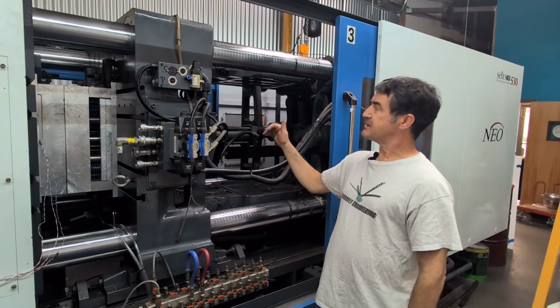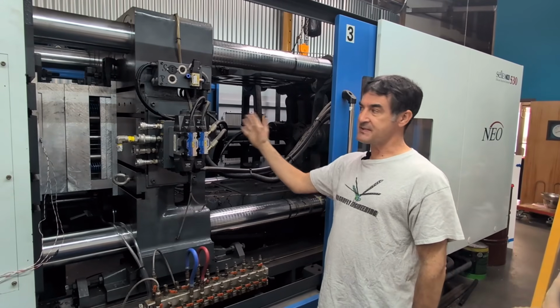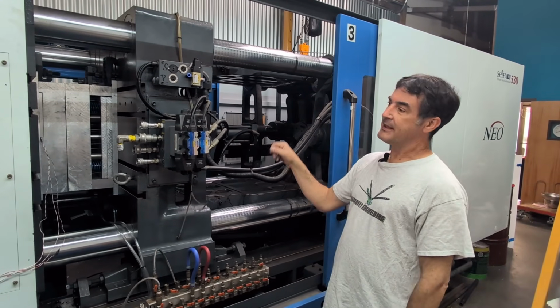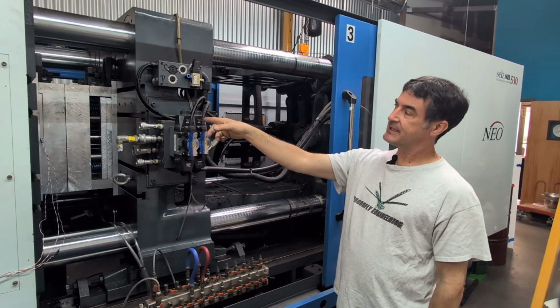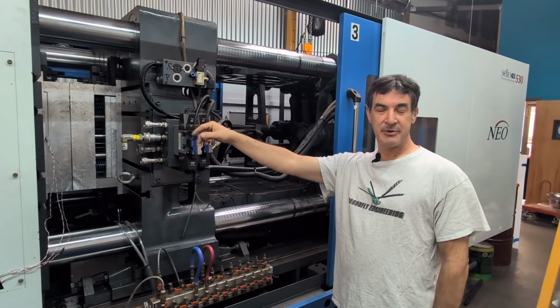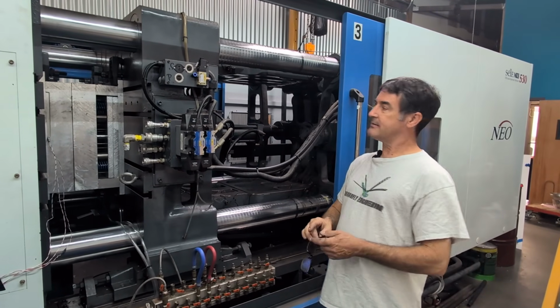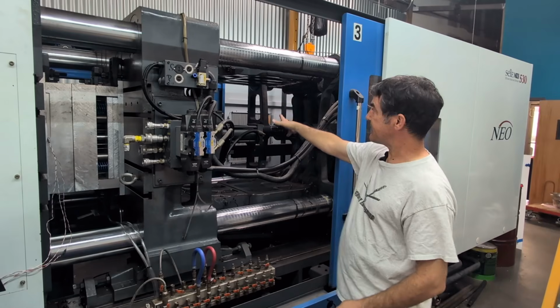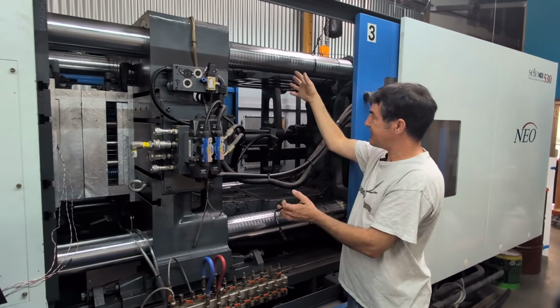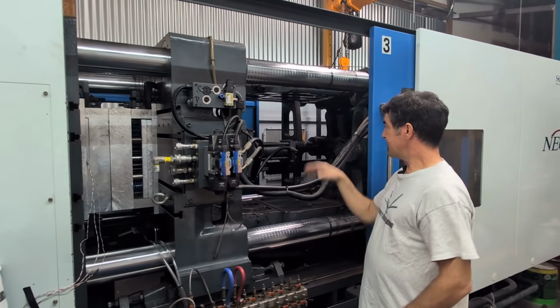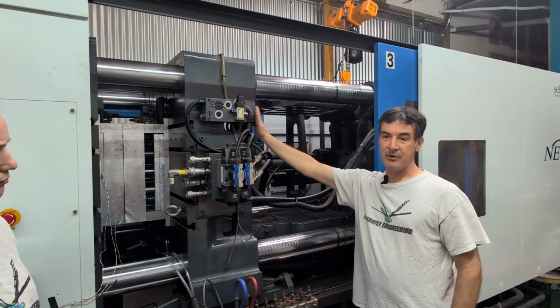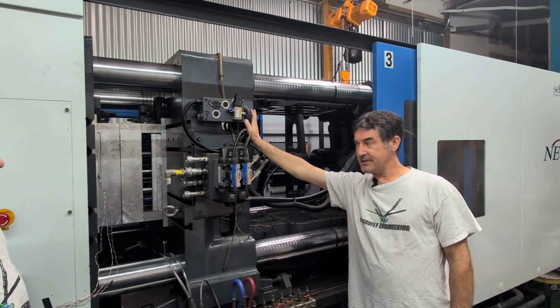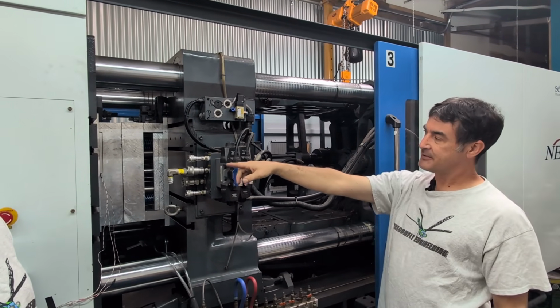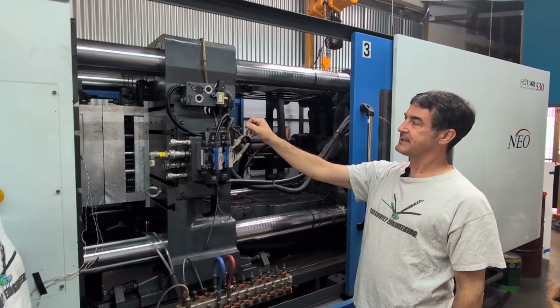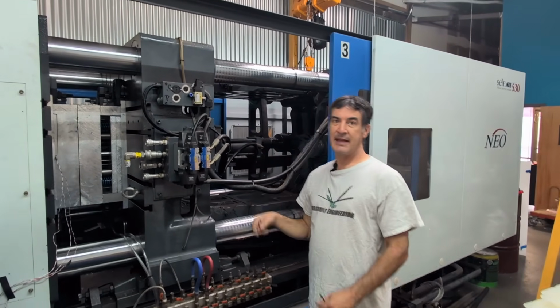So the molding machine clamp will then close after the last part is ejected, and then the nozzle will advance to the opening in the front of the mold. At which point, when the toggle clamp locks up, which is kind of like a vice grip, the clamp is holding the mold shut with 500 tons of force, and then the injection unit will advance forward, inject plastic into the mold cavity at very high pressure.